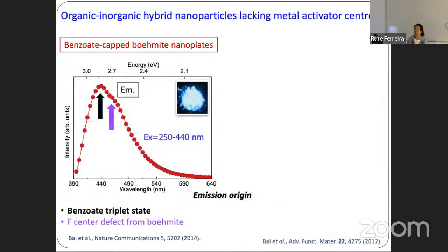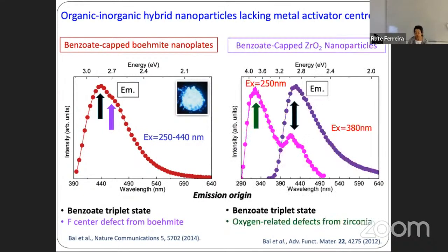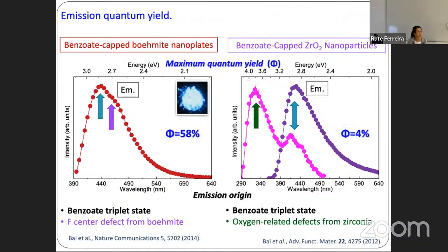In what concerns the emission, we have a broadband emission in both cases. For the boehmite nanoparticles, the emission is a combination of the benzoate triplet state and of the F-center defect. And of course, in the case of the benzoate zirconia, we have also the contribution of the benzoate excited state, and some oxygen-related defects are also contributing to the emission. And the very intriguing aspect is that the quantum yield is really different despite all the similarities that I have been showing. Whereas the quantum yield for the boehmite nanoparticles is 58%, for the zirconium-based ones, we end up with a maximum value of 4%.